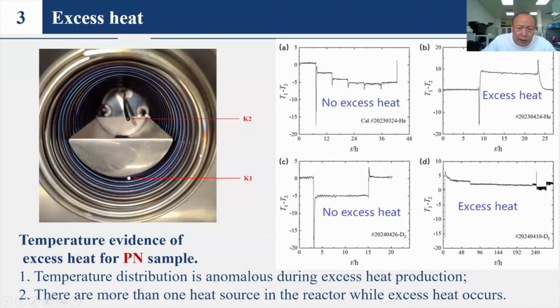There's another piece of evidence of excess heat. We use 2 thermocouples. One is beside the holder, another is above the holder. The y-axis is the difference between thermocouple 1 and thermocouple 2. We can find if there is no excess heat, the difference is a negative value. If there is excess heat, the difference is a positive value. It means if there is excess heat, the temperature T1 is hotter than temperature T2. It means there is a heat source in the holder. Yes, this is another evidence of excess heat.